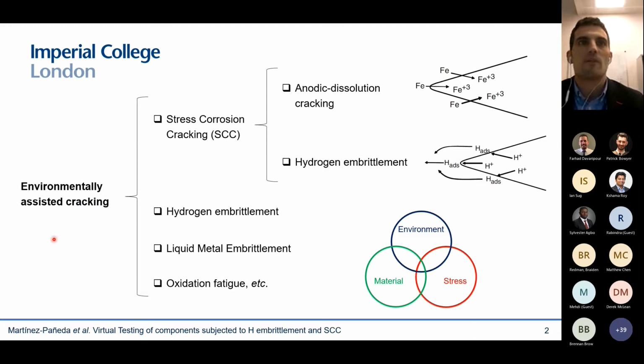Within the broad term of environmental assisted cracking, we have multiple categories, one of which is stress corrosion cracking. And stress corrosion cracking can be divided into two groups as well: anodic dissolution cracking processes and hydrogen embrittlement. And you will see that hydrogen embrittlement appears twice in this slide. The reason being, of course, that you can have hydrogen embrittlement in a corrosive environment where hydrogen ingress is a result of the corrosive reactions. But you could also have hydrogen embrittlement in the absence of an aqueous electrolyte, for example, when you have components exposed to hydrogen gas.